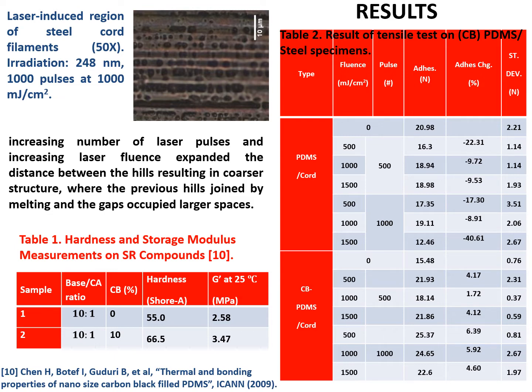The results of our experiments are shown on this slide. On the upper left, we see an optical microscopy photograph of the irradiated area. We can see the ripple structure created when we applied the 248 nanometer laser using 1,000 pulses at 1,000 millijoule per square centimeter fluence. Increasing the number of laser pulses and increasing laser fluence expanded the distance between the hills, resulting in a coarser structure where the previous hills joined by melting and the gaps occupied larger spaces.